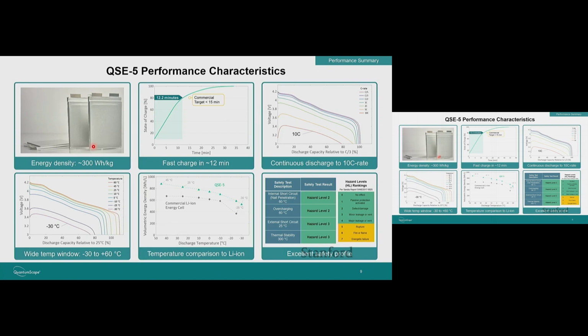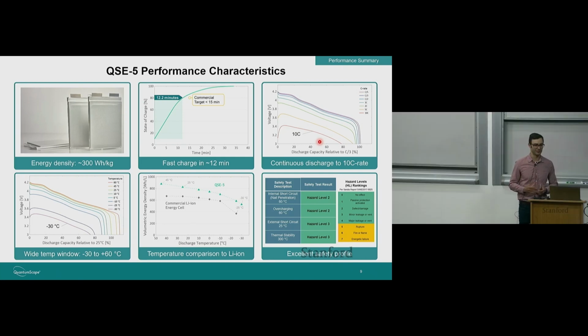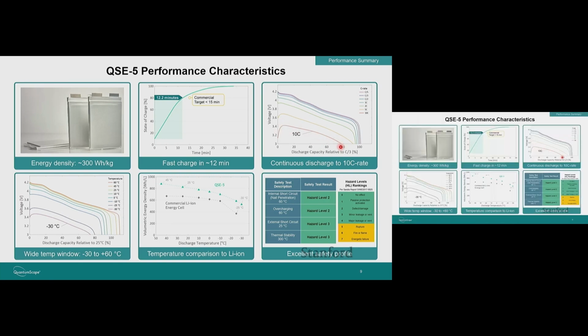This chart on the top right shows the rate capability of the cell as you discharge at faster and faster rates. A typical automotive cycle would be if you're driving aggressively on the highway, you can fully discharge a battery in about 3 hours. That's called C by 3, C divided by 3 in battery parlance, because it takes 3 hours to discharge a battery. And we're showing up to 10C, meaning 6-minute discharge. So it's kind of ludicrous to take a long-range electric vehicle and try and discharge it in 6 minutes. But if you need extremely high-power pulses to accelerate, you want to drive on the track, you want to do a drag race, this battery is capable.